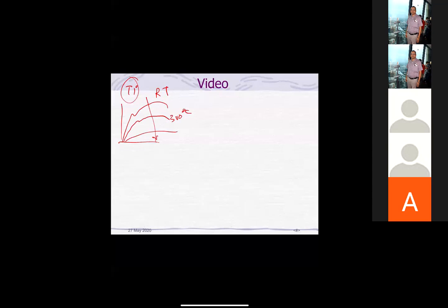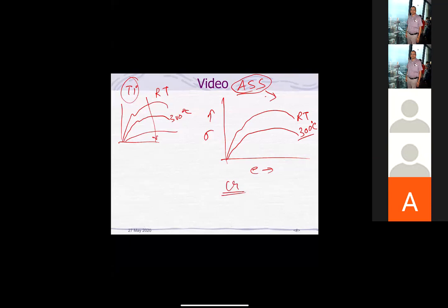For example, austenitic stainless steel. This is another material I'm going to discuss today. If you see ASS, let us say this is the stress strain diagram at room temperature. Now you increase the temperature to 300 degrees centigrade. Let us say this is 300 degrees centigrade. We are discussing this for ASS. But now what happens, due to the presence of chromium, there is a phenomenon called dynamic strain aging regime, also called the Portevin-Le Chatelier region.